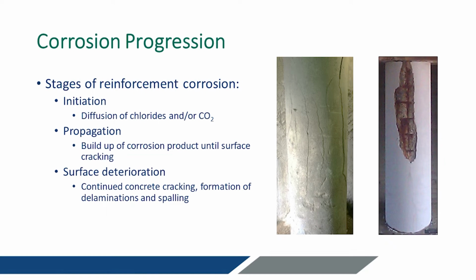With anything, we're dealing with corrosion. Obviously there's the initiation phase, where chlorides get into the concrete. They cause the activation of the corrosion. That corrosion expands and causes cracking and delamination of the concrete.